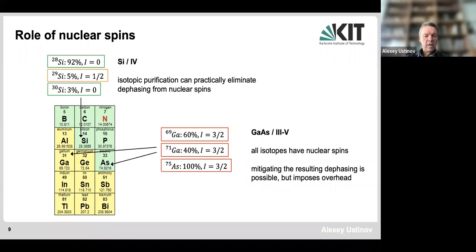And these nuclear spins act as a decoherence bath, as a noise source for the electron spins of the dots. So you see all the gallium isotopes, of which there are two actually with major abundance, used in these gallium arsenide structures, are both magnetic, and they cannot be used as a neutral medium. In contrast, silicon and germanium can be made of really isotopically spin-free states, and making isotopically purified silicon is a quite well-established technology in the semiconductor field, and one can have a technique to remove the silicon-29 isotope to completely eliminate dephasing due to the nuclear spins. Therefore, this is a much more promising technique, using group 4 semiconductors rather than 3-5 semiconductors, for this type of technique, due to the role of nuclear spins.